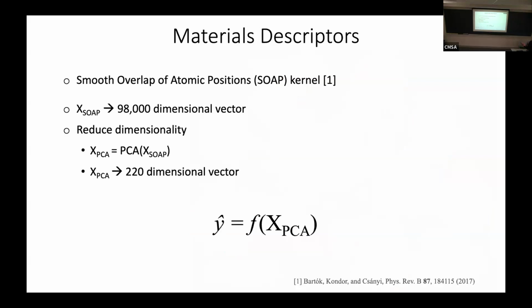The issue with this SOAP vector, which I think is why it's maybe not used super often, is that it can be really high dimensional. There are 98,000 dimensions in this SOAP vector. That's too many for us to learn with a small number of data in our data set. It didn't really work for 700 data points. And so we use PCA to reduce the space to about 220, and that seemed to work pretty well for modeling the data. So our input to our AI model is a PCA-compressed SOAP vector, which we then can use to predict the formation energy and the magnetic moment.